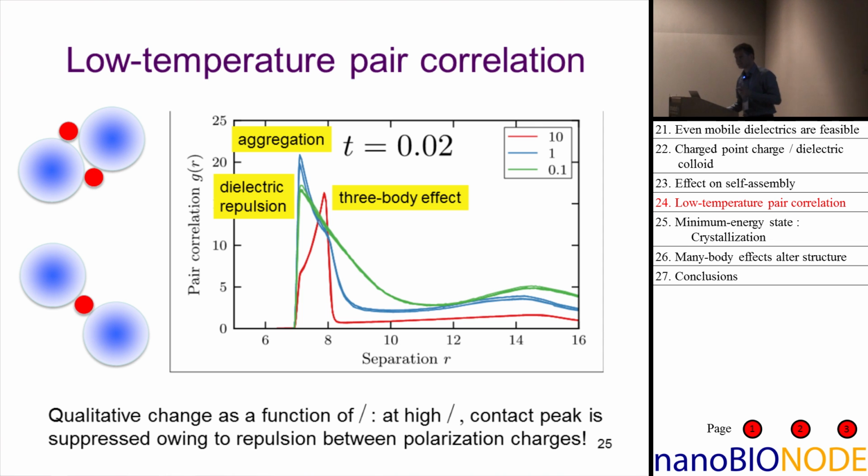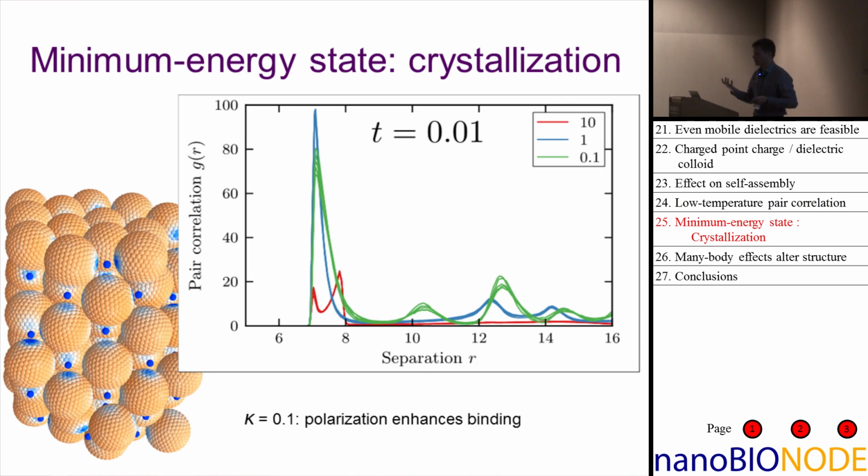First, let's take these colloids, let's say in water. What you get is a sodium chloride structure where the small negatively charged particles hold together the positively charged particles. So there's this orange glow on the particles because the color coding here indicates the total charge, so free charge and induced charge. So the whole thing is held together in a sodium chloride structure, but you see that the small particles actually don't want to touch the colloids because they induce their own repulsion.